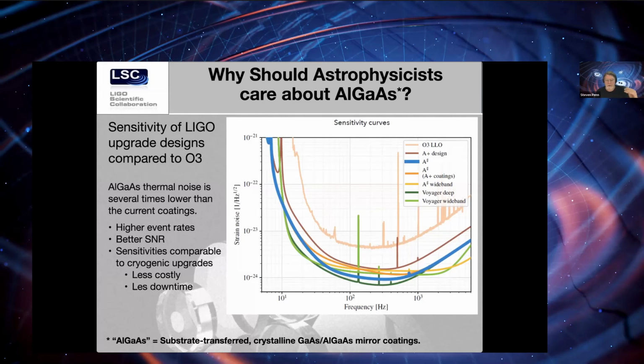AlGaAs coating thermal noise is several times lower than the current coatings. And in fact, when we see these published noise curves, they only list the upper limit of what we think the coating thermal noise is. We're trying to complete measurements this summer, as I'll refer to later, that are going to measure it directly. But right now, our coating thermal noise apparatus is not sensitive enough to measure the actual coating thermal noise of the AlGaAs coatings because it's so low.